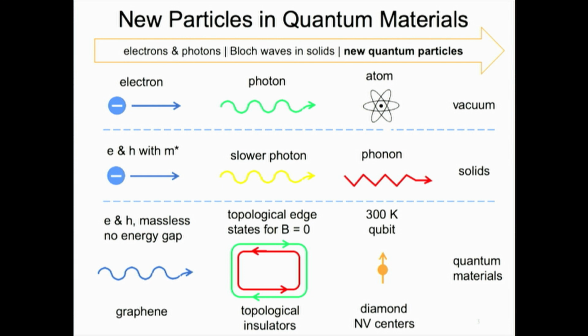And you can do things like in the quantum Hall effect, where you can have edge effects if there's a strong perpendicular magnetic field, where the edge states go around the sample, as shown here by the red orbit, where nothing's going on in the middle, the electrons just go in circles. But if you have a topological material, the strong spin orbit coupling in this class of materials acts like a magnetic field and gives you edge states in zero applied magnetic field. And so you just have a sample that you pick up off the table, and it's showing the quantum Hall effect just the way it is. And so this is entirely different than people are used to thinking about.